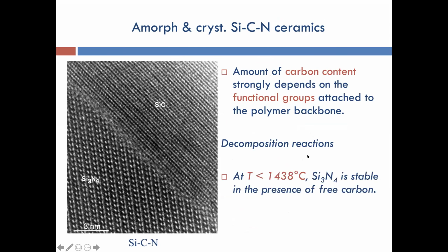For example, at temperatures below around 1400 degrees Celsius, silicon nitride is quite stable in the presence of free carbon. But when you go to temperatures above 1850 degrees Celsius and so on, silicon nitride can dissociate. Again, beyond 1500, silicon nitride can already react with carbon to form silicon carbide with the formation of nitrogen gas, which means the decomposition reactions are already active at 1500 degrees Celsius and above. So these materials obviously cannot be used at 1500 degrees Celsius and above. Therefore, that limits the high temperature application of silicon carbonitrides.